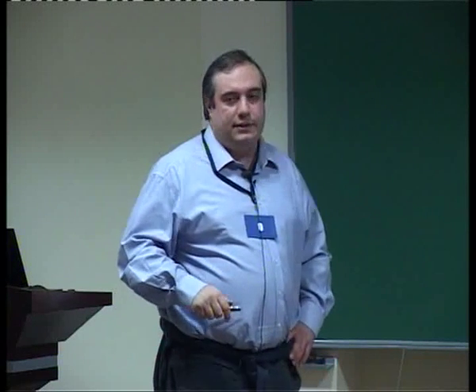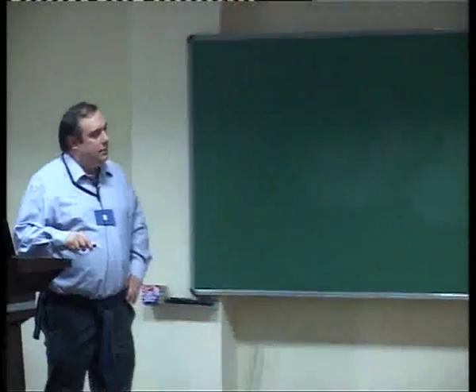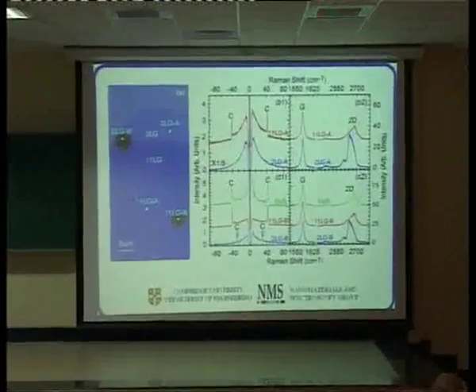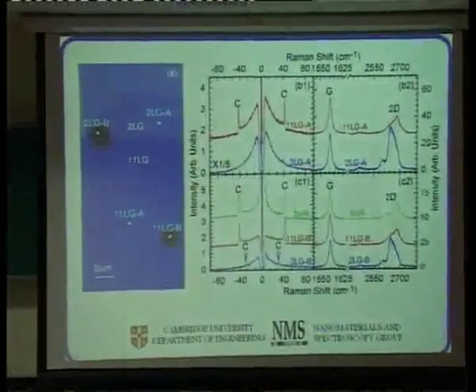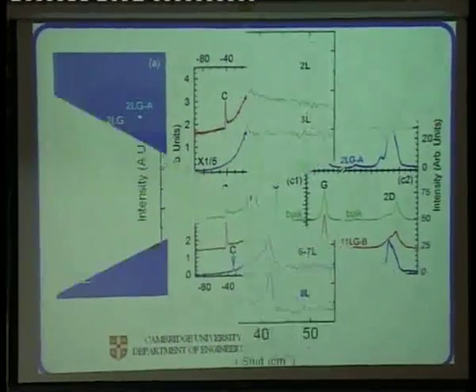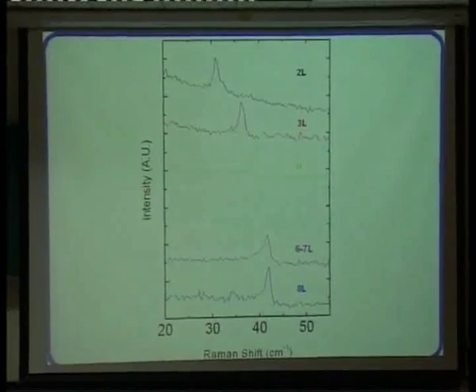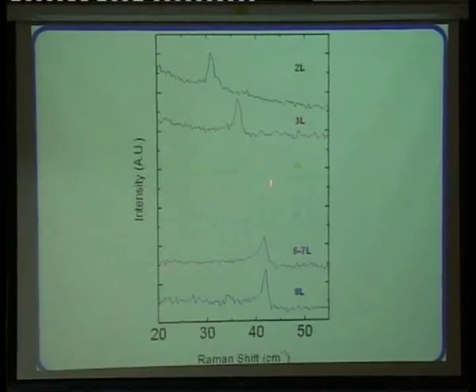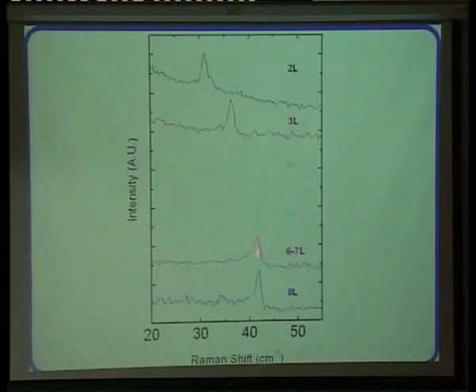Of course, if you want to get rid of the silicon, what you can do is to drill holes in the silicon substrate. You put the graphene on top of the hole, then you don't have the silicon anymore, and the measurements become much easier. And as you see here, this is the bulk, 11 layers, 2 layers. The C peak appears very nicely, and you can study it. So it does exist, and you can see that the position of this peak actually changes with the number of layers, as you would expect, from 2 to 8 layers.